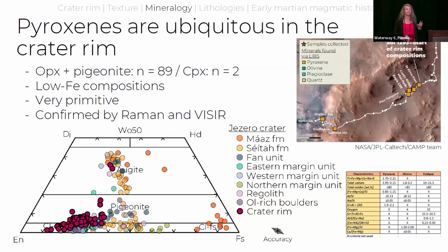Let's switch to the mineralogy. So what's really cool with the LIBS, it has a beam size that varies between 150 micron to 450 micron, depending on the distance to the target. And using stoichiometric data that you can see here in this table on the lower right, it's too tiny, it doesn't matter. This is really just a variable that we use to detect if we have in our beam analysis, our point analysis, one single pyroxene, olivine, or plagioclase.